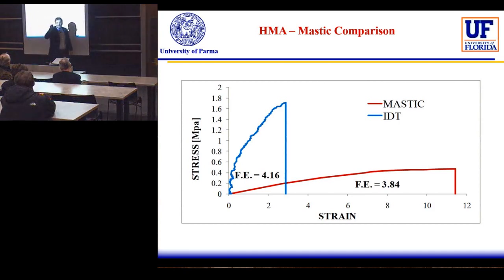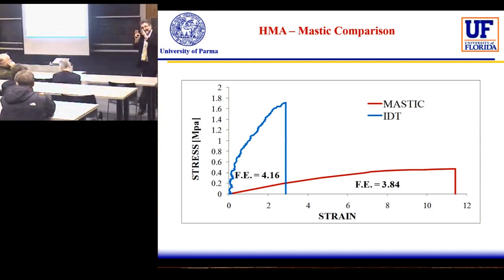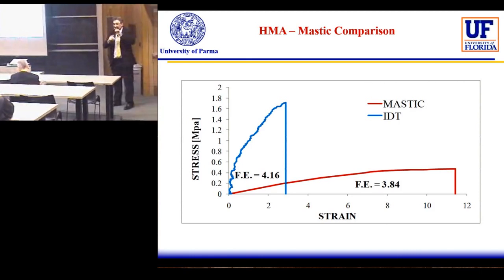So when we have the first coalescence of when the micro crack appears, we have the first crack. The idea is to try to avoid the problem, that is, to take the first. But is this the conventional definition of fracture energy? Fracture energy is the energy flux to a propagation of a macro crack. It's not a micro crack.